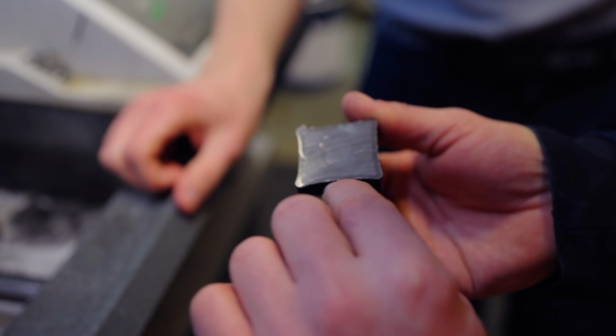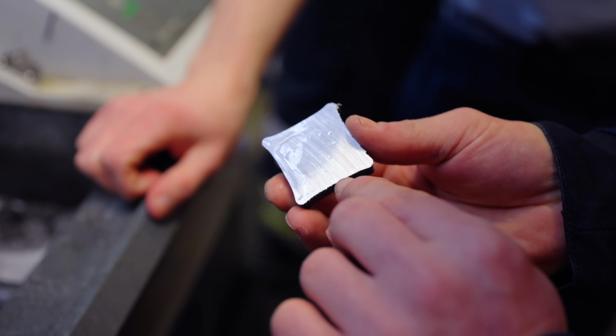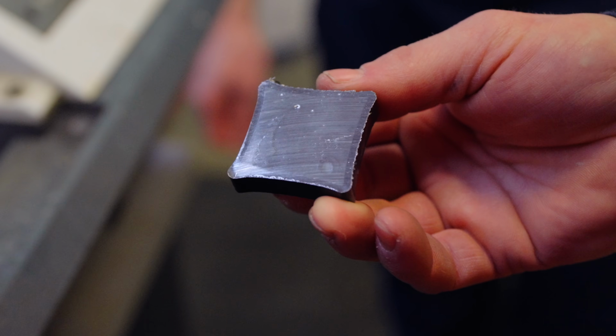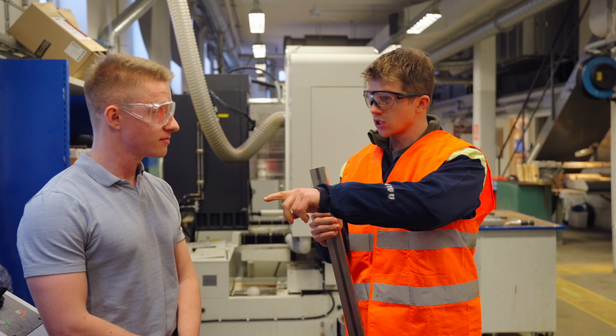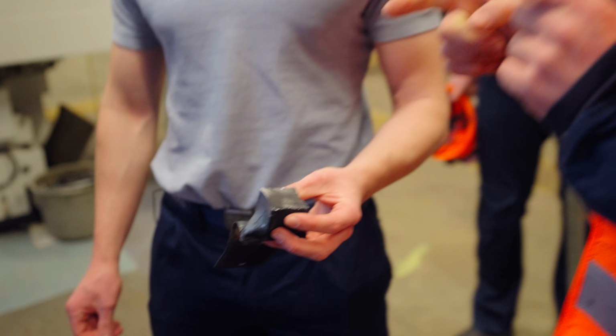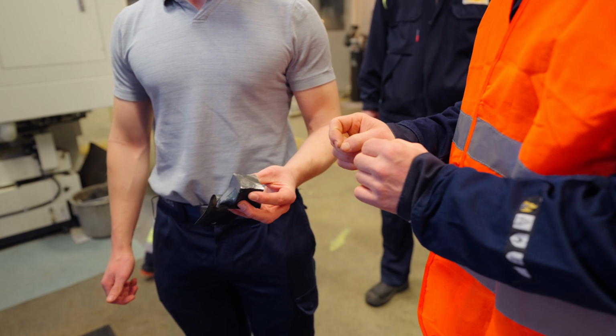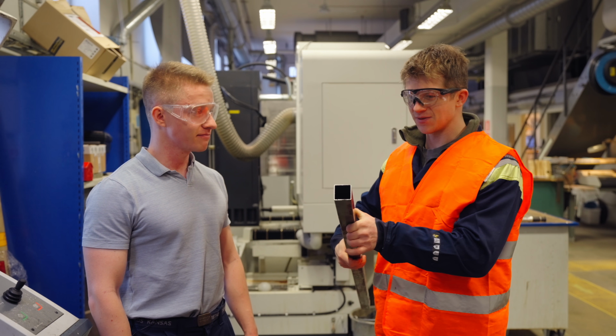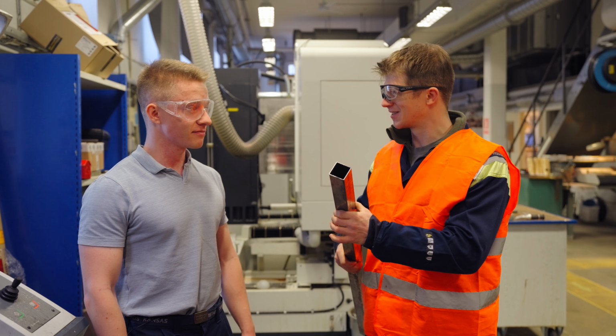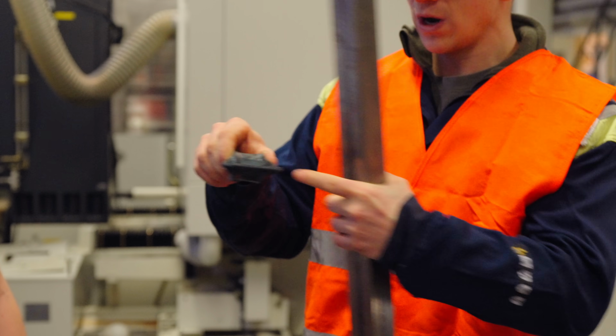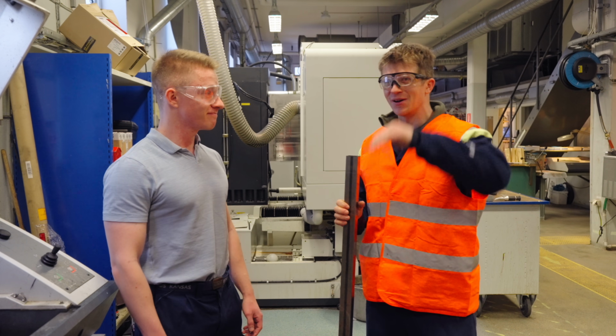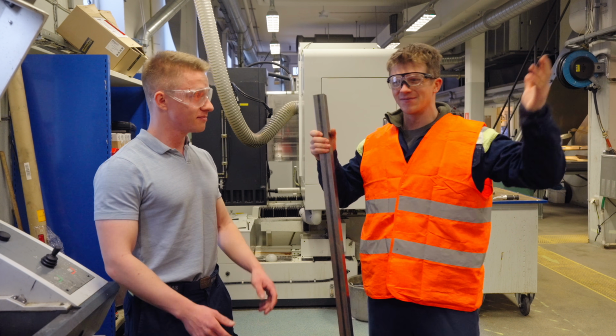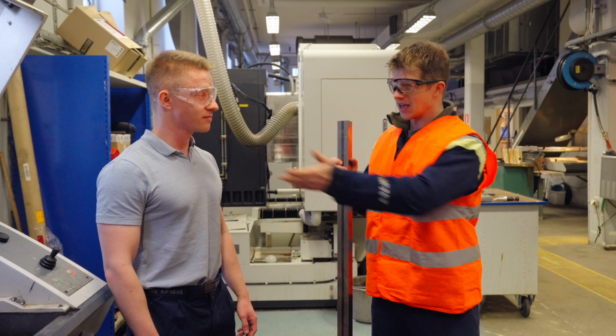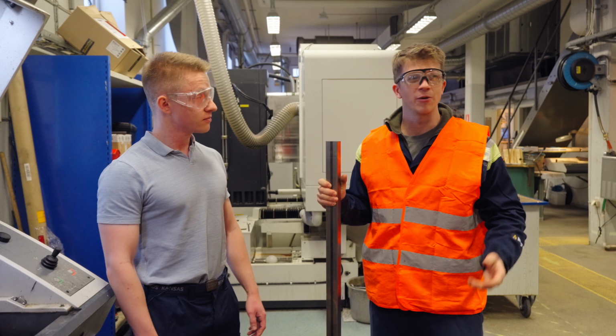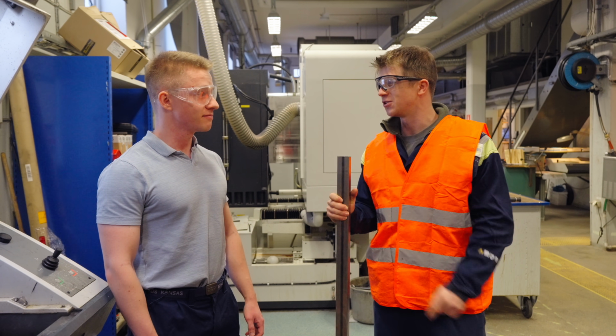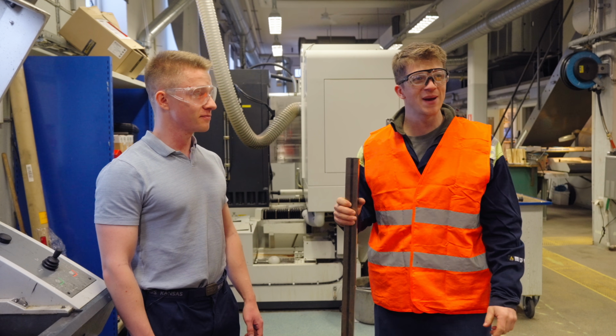Super nice surface finish. Oh, and you can see the jacket from the hipping and then the actual alloy they want to test in the middle. So the piece that we just looked at is an R&D sized test from the hipping, and it literally is made out of powder filled in a bit of regular steel tube. Yep. They crimp it, weld a seam, it goes in the massive hipping chamber on top of an enormous canister, and then ta-da, you can test and look at these samples and see exactly how things are looking on a much smaller scale without having to use 1.5 tons of powder.